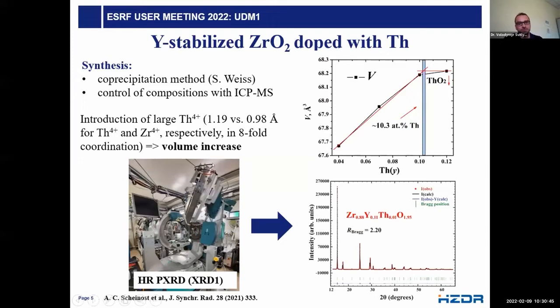On the ROBL beamline, we have two diffractometers, and this is XRD1, the high-resolution powder diffractometer. With this machine, you can get a resolution of up to 10⁻⁴ Δd/d. And very recently, actually last weekend, we commissioned a new detector with a smaller pixel size, and we further increased the resolution up to almost 10⁻⁵ Δd/d. And you can get excellent powder diffraction data and perform quality refinement of structure.